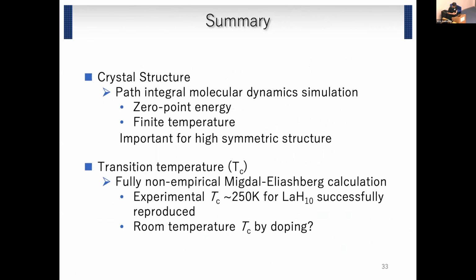Okay, so let me conclude. In the first part, I discussed the crystal structure of the system. We found that both zero temperature quantum effects and temperature effects are important to stabilize the symmetric structure. And for TC calculation, we found that non-empirical self-consistent Migdal-Eliashberg calculation gives a reasonable value for LaH10 and also H3S. And maybe by doping, we can enhance the TC.